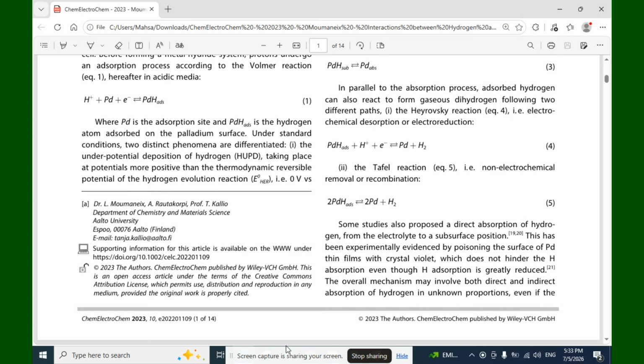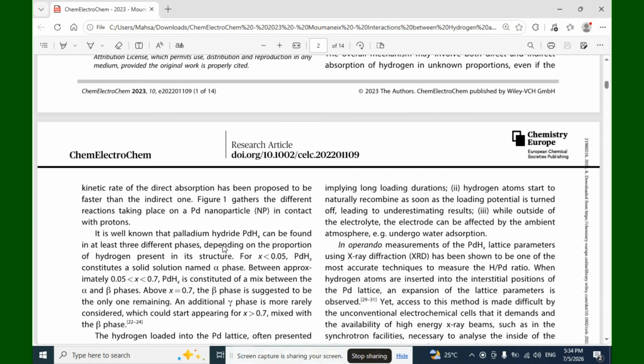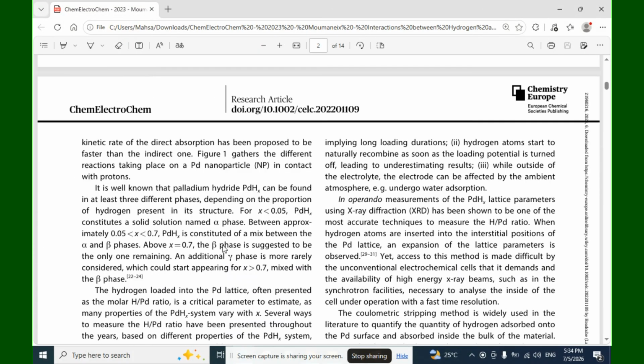Some studies also propose a direct absorption of hydrogen from the electrolyte to a subsurface position. This has been experimentally evidenced by poisoning the surface of palladium thin films with crystal violet, which doesn't hinder the hydrogen absorption, even though hydrogen adsorption is greatly reduced. The overall mechanism may involve both direct and indirect absorption of hydrogen in unknown proportions, even if the kinetic rate of the direct absorption has been proposed to be faster than the indirect one. Figure 1 gathers the first reactions taking place on the palladium nanoparticles in contact with protons.